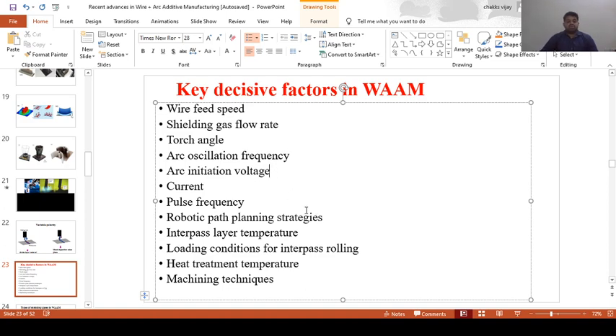Generally the arc initiation voltage is very, very important. For example, for the first pass we generally give a very high voltage, because especially the first bead should properly anchor with the base metal. If we are not giving a very high voltage, then eventually after developing 3 or 4 layers, this first layer will get peeled off from the base plate, which will cause a lot of mess. So initially we give a very high arc voltage, so that dilution takes place with the base metal, which causes an anchoring effect for developing the subsequent layers. So this arc voltage is one of the most concerned parameters.